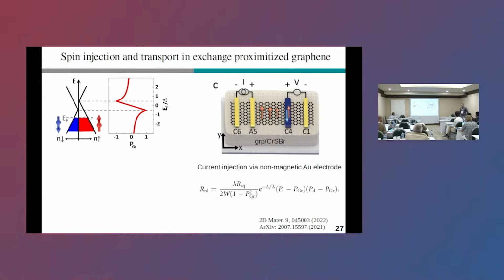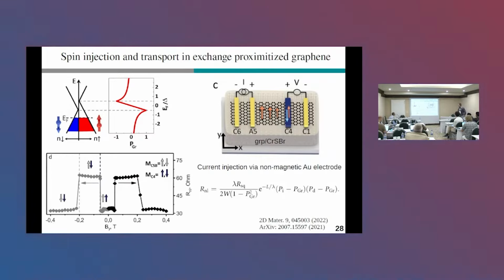And now let's see if graphene really is polarized. This is what they measure. At 0 field, they measure a low resistance state, which means the graphene and the detector, the cobalt, are parallel polarized. At some field, the cobalt switches and we go to a higher resistance state. And at an even higher field, the substrate switches, which brings us back to a low resistance state. So when the substrate switches, the proximity exchange switches, and this means also the polarization in graphene switches. And this experiment very nicely demonstrates that we can use proximitized graphene for spin injection without the need of conventional ferromagnetic electrodes.